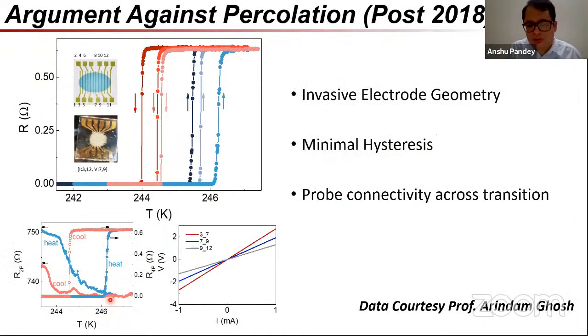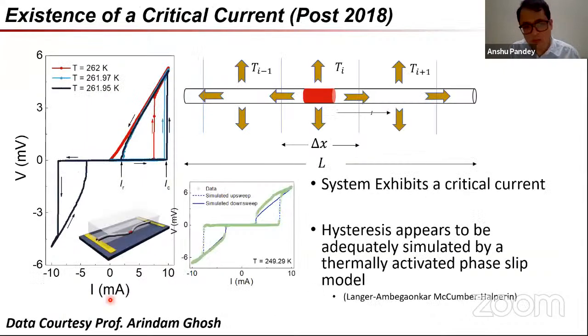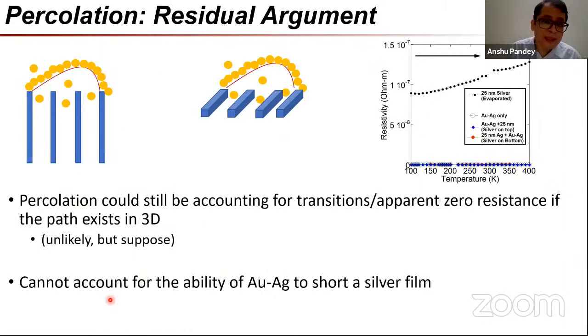They also furthermore use a fully invasive probe geometry, which is much more useful because at least in 2 dimensions, the question whether the path does not follow the current path and does not intercept the voltage probes gets ruled out at least in 2 dimensions. He was also able to observe features such as critical current, which are very, very indicative that this material does have, or is associated with, a state which, as far as possible, resembles a superconducting state.